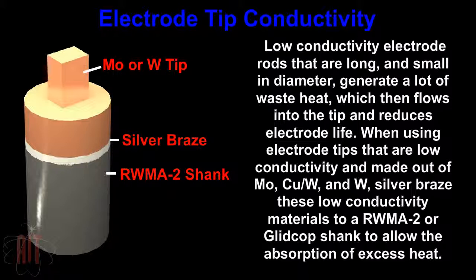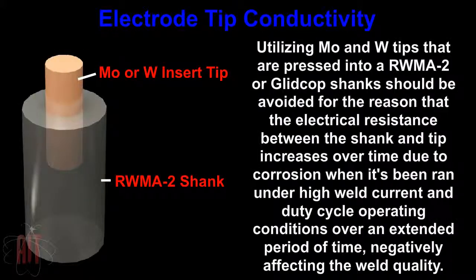When using electrode tips that are low conductivity and made out of molybdenum, copper tungsten alloy, and tungsten, silver braze these low conductivity materials to a RWMA-2 or Glidcop shank to allow the absorption of excess heat. Utilizing molybdenum and tungsten tips that are pressed into RWMA-2 or Glidcop shanks should be avoided, because the electrical resistance between the shank and the tip increases over time due to corrosion when run under high weld current and duty cycle operating conditions over an extended period of time, negatively affecting the weld quality.